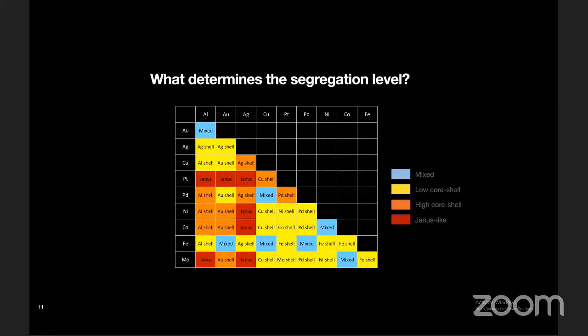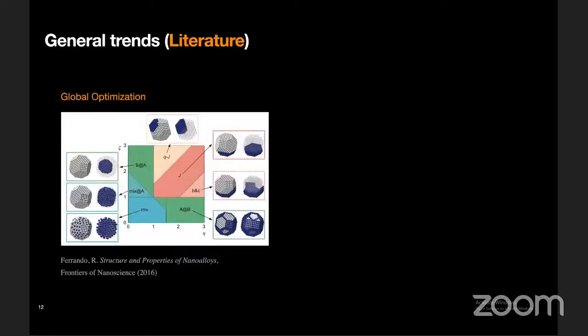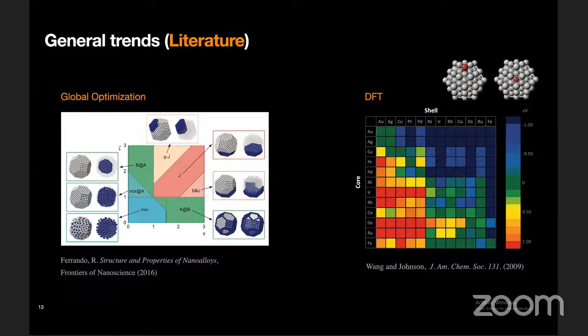So once we have these results, we investigated further to find the hidden trend, the rules that determine the segregation level for a given combination. So essentially the question was, what makes a certain metal more core preferring and the other more surface preferring? There is some comprehensive work on this topic that inspired our work here. For example, a global optimization technique was used to find the core shell preference. It showed that many different types of bimetallic structures are formed depending on the interaction energies. And there are also DFT studies where they found this sequence or the ordering of the metals that reflects how strongly a metal tends to occupy the core.